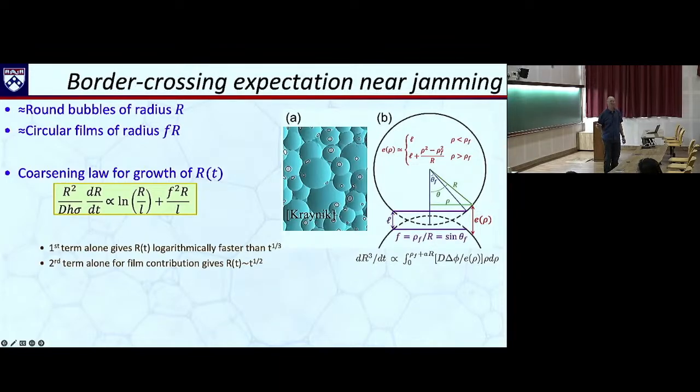It can't be flat because there's a pressure difference between the bubbles. So it has to be curved. But it's curved on a scale that's small compared to the size of the bubbles. So assuming it's flat as I did here is not a bad approximation. But it is absolutely an approximation. That's why the equation doesn't have any information about the curvature.